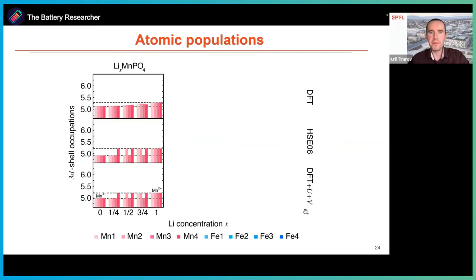Now let us look at the atomic populations. These are Löwdin populations. So here I show three panels. The top panel corresponds to the atomic populations computed at the DFT level. The middle panel corresponds to the populations computed using another popular method, HSE06, which is a hybrid functional, which is computationally extremely expensive, but gives much better results than DFT. And finally, the bottom panel shows the populations computed with our method, DFT+U+V.